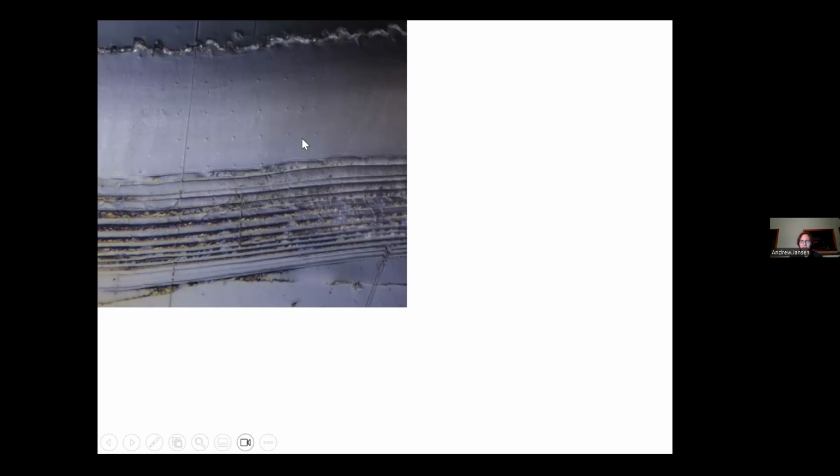You can see this grid of triangles on there. That's from a mechanical test that I did. It's called nanoindentation. Still working on analyzing that data. But the more important thing is that you have a well-defined area that has helicoidal microstructure, and then you have an area down here which has a large number of layers where the fibers are facing all in the same direction within each of these. So you have an exocuticle and an endocuticle that are pretty easy to spot.